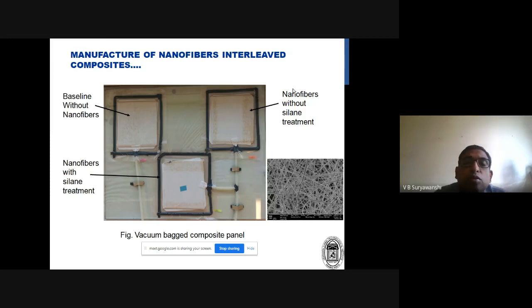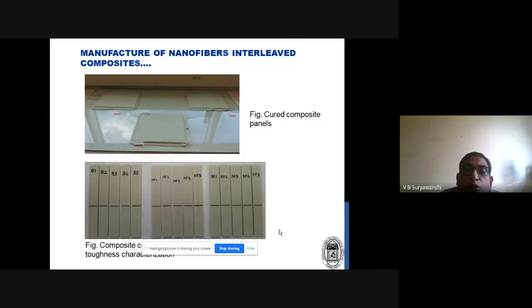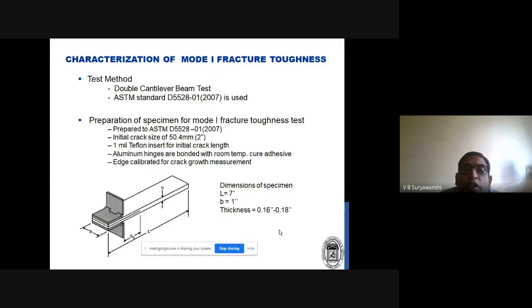By separating them out. So this is the actual picture of the manufacturing process. On the left hand side top figure, without nanofiber. So there is no nanofiber mat in this composite. Then on the right hand side top, nanofibers without treatment. Treatment is something we do to have proper bonding with the polymer. This nanofiber mat is chemically treated. So some chemical agent is applied to that. That is what is called the silane treatment. So without treatment and with treatment, that kind of experiment we had done. And then we made three composites and we tried to understand whether it improves the performance.